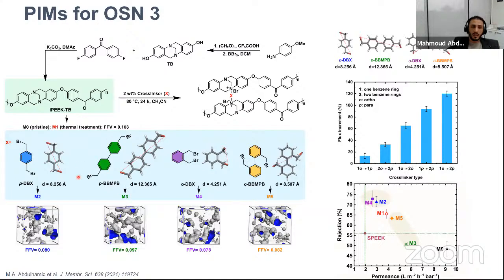If you use a longer cross-linker, that will make more space between the chains, and thus you have a higher flux and higher permeability. If you use a para, it will also give higher flux compared to ortho. So we generated this curve to show, if you want to select a cross-linker for this type of material and this specific application, which could be applied also to other applications, you could look at going from 1 ring ortho to 1 ring para. For example, this 1 ring ortho and this 1 ring para. If you take this one instead of this one, you have an enhancement of 15% in flux.